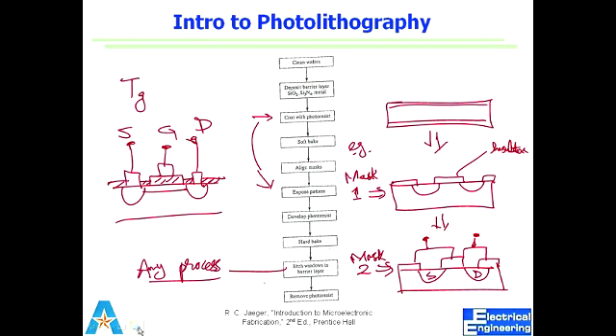But generally the idea, the whole process of lithography is we clean the wafer, we deposit the protection layer, whatever hard layer we're going to use to transfer the pattern. It can be silicon dioxide, silicon nitride, metal, right? Whatever. We coat it with resist. Then we do soft bake. Why do we do soft bake? Why do we call it soft bake? Two questions. Why do we do soft bake? I have just put my resist down. Why do I want to heat it?